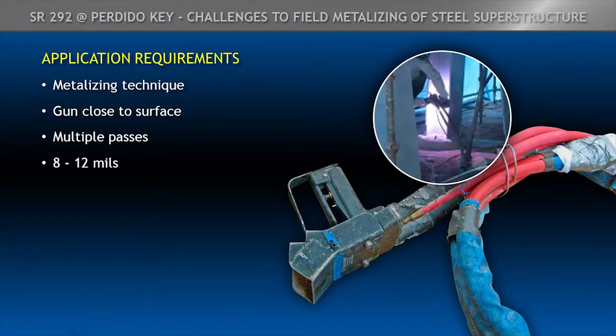The metalizing technique, we checked with the applicators as they did it. As you can see by the picture, you have to have the gun extremely close to the surface as compared to an airless spray gun. And you have to make multiple passes. This electric arc gun comes out in two wires, and as the wires cross, it's heated to about 1200 Fahrenheit, and the compressed air feeds it to the steel in molten drops. So to get a coating there, you have to do multiple passes with those molten drops hitting the steel. And we look for 8 to 12 mils. And by doing the multiple passes, you also encourage the adhesion between passes to avoid any type of cohesive break in the metalizing.